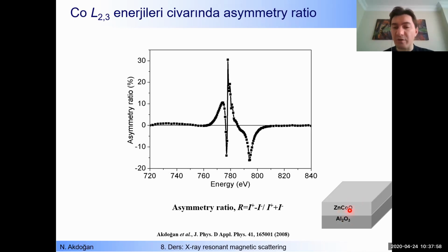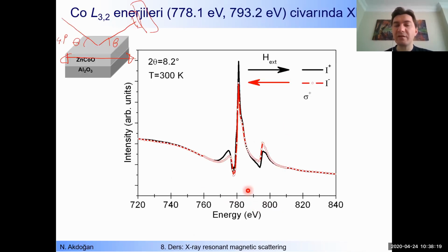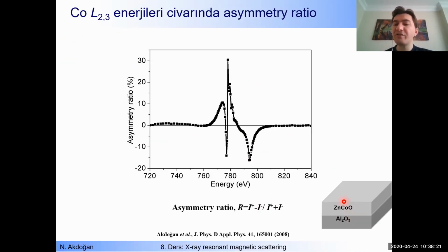But in addition to cobalt, here we have oxygen and zinc elements, okay? What about their contributions to the magnetization? We know that the pure cobalt metal in periodic table, if you consider cobalt element, cobalt is ferromagnetic and it should give magnetic signal like this. It is expected. But oxygen is paramagnetic, okay? It is not expected to give such signal. And zinc is not magnetic, okay? We don't expect any signal from the zinc.